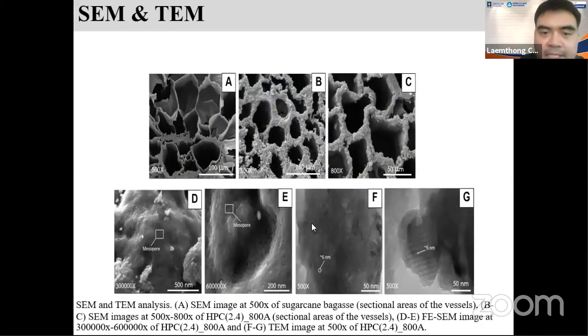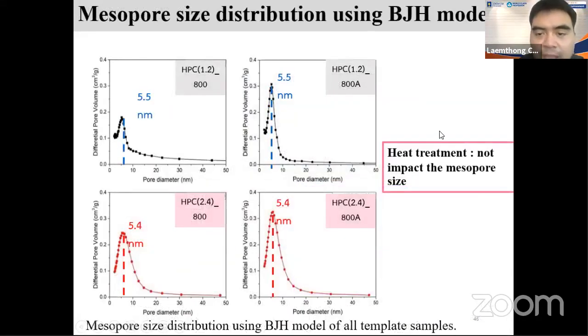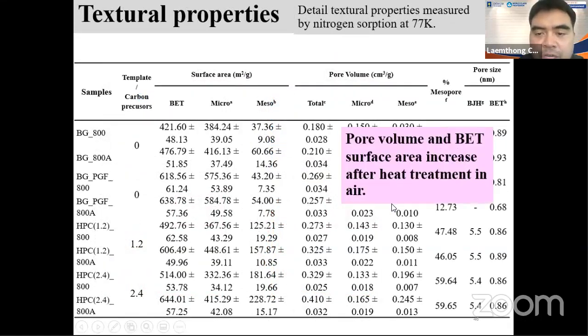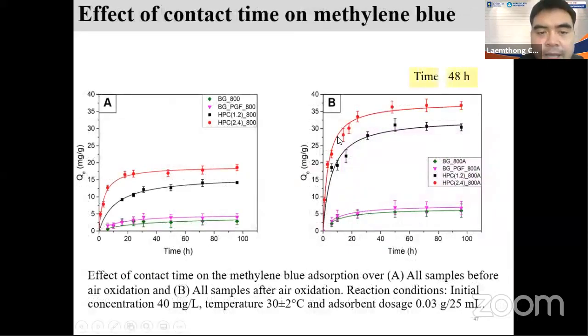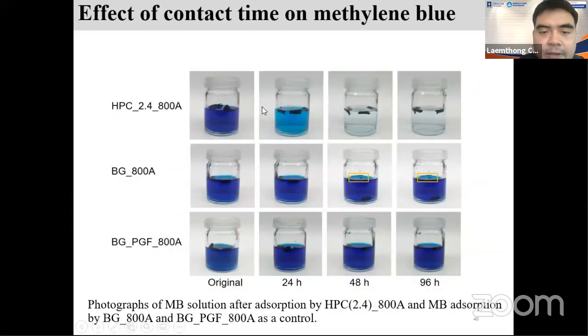We use some other techniques to determine the surface area and also the porosity. And we can actually see the porosity as well in this case. Okay, we measure the pore size distribution and the surface area and so on. And we try to adsorb methylene blue and two other dye products as well. Okay, and let's see here. This is the best product that we obtained, the top one.